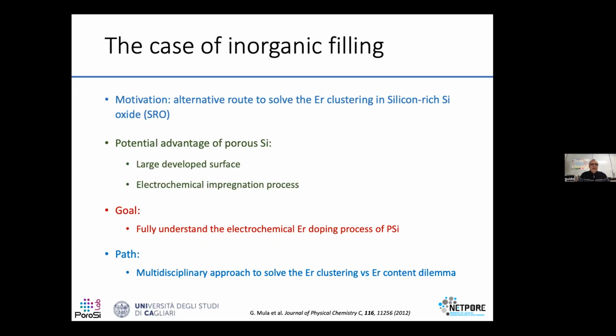porous silicon will allow a larger developed surface as a place where to distribute the erbium correctly, and the flexibility of the electrochemical impregnation process will allow also some flexibility in addition to the surface. So to achieve the result, you need to fully understand how the electrochemical process goes on, and you need to use a multidisciplinary approach to understand and solve this dilemma between erbium clustering and erbium content for the optimum result.